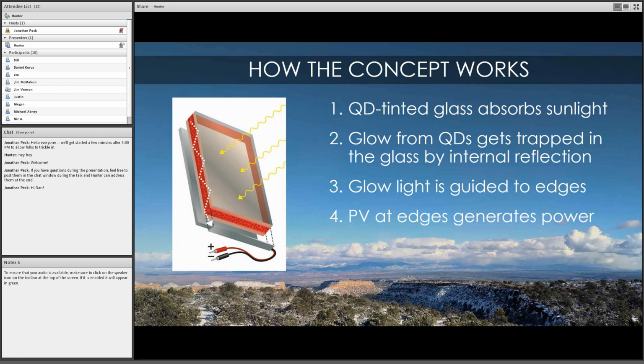That luminescence, about 70% of it gets trapped in the glass by total internal reflection, and then the light has nowhere else to go but towards the edges where it can couple out. And so I'll show a picture on the next slide or two that shows the effect a little bit better, but you can put solar cells right there on the edge to capture that light and generate electricity. So a simple idea: tint a window with quantum dots, capture the light that they emit at the edges, put solar cells there, and save the world.